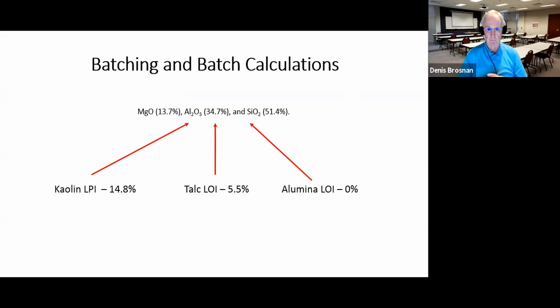You got to batch this together. You got to make a batch calculation. So you've got a goal of a certain amount of magnesia, a certain amount of alumina, a certain amount of silica, and we've got a chemistry with a loss on ignition. That's supposed to read LOI 14.8%, talc 5.5%, and alumina none. So to meet this composition on a calcined basis, we have to start with a kaolin composition on a calcined basis. So the composition without any loss of ignition. We'll start with a talc on a calcined basis. And we'll mix alumina, calcined talc, and calcined kaolin together in certain proportions to get that composition.